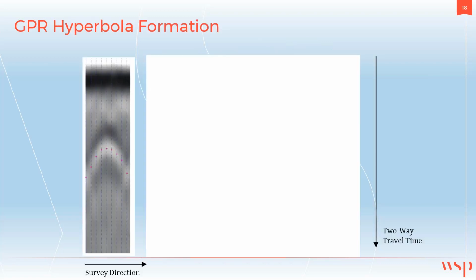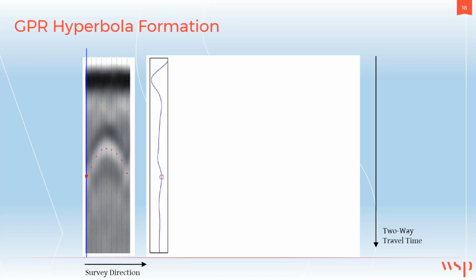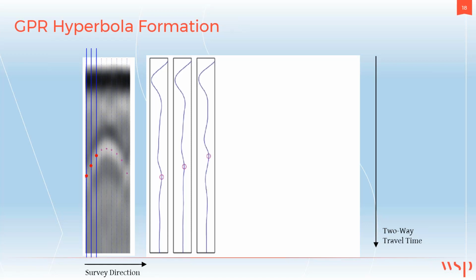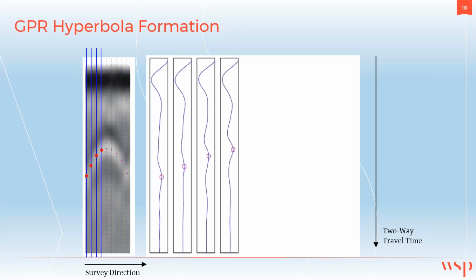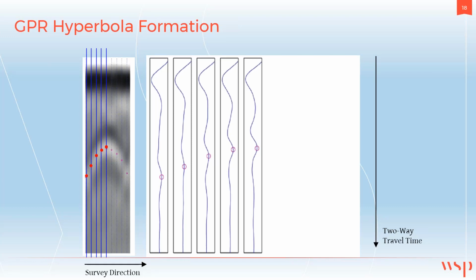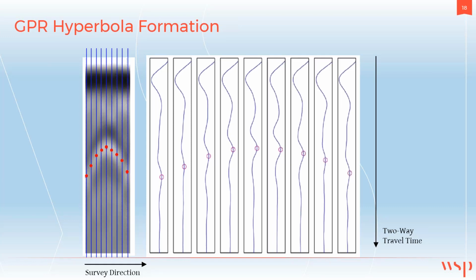The reason we see a hyperbola is because we interpret the signal as being purely into and out of the surface perpendicular to the scan surface, but the actual signal goes in a conical effect. So as you are scanning across and approaching a reinforcing bar, the time of travel implies that the bar is deeper when you're also laterally away from the bar. As you approach the bar, it actually appears to be shallower and shallower until you reach the point where you're directly over the bar, and that's the apparent peak of the hyperbola.